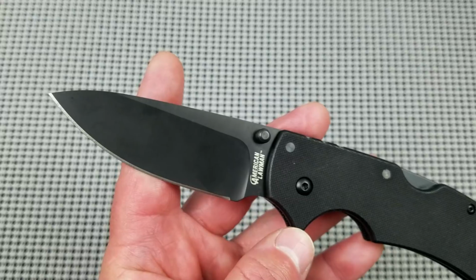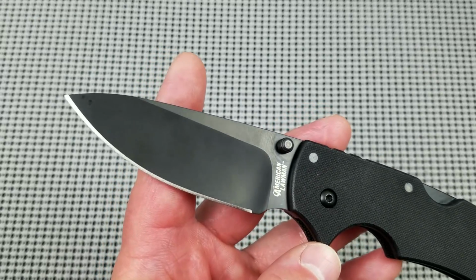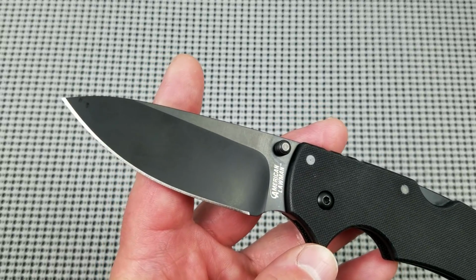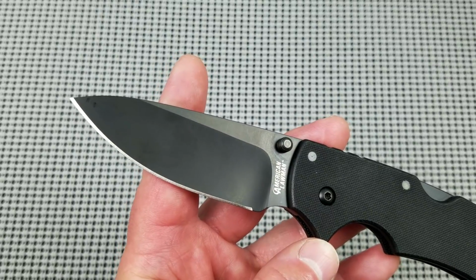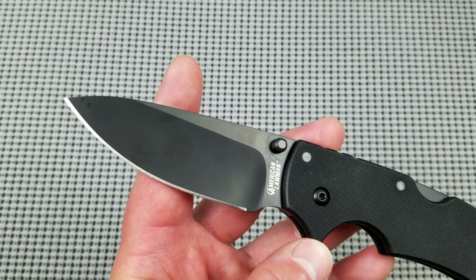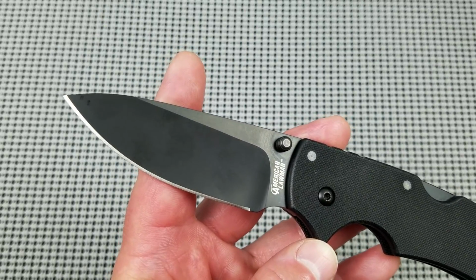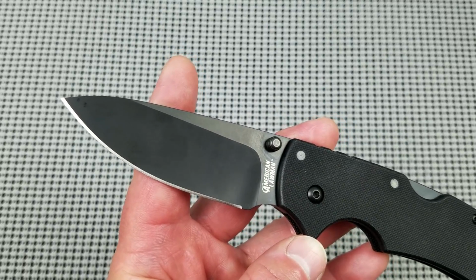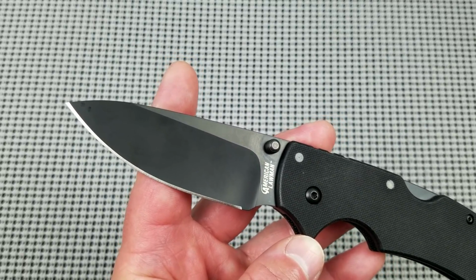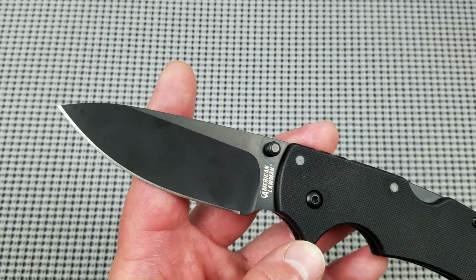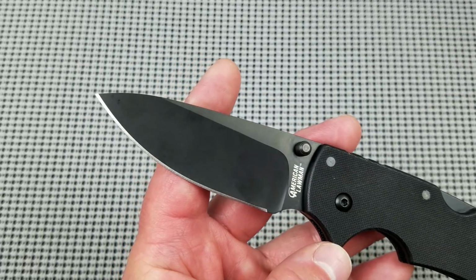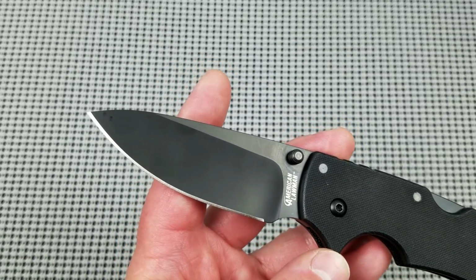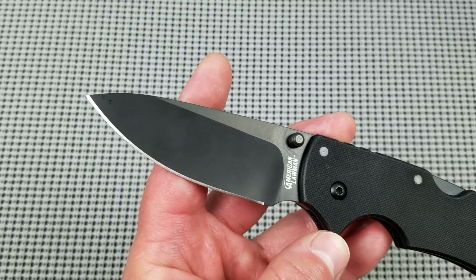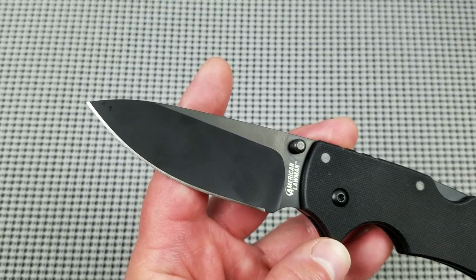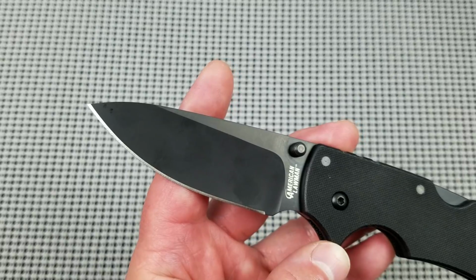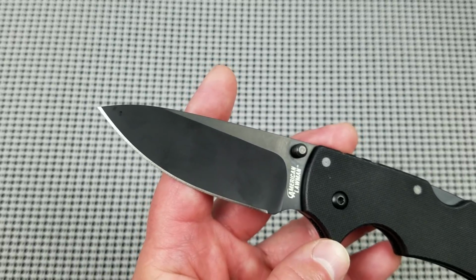So what you end up with is the best features of both of those steels. You get the extended edge retention of D2, but much higher levels of corrosion resistance of, say, a 440C. It's a very, very interesting steel. The max Rockwell typically is about 64.